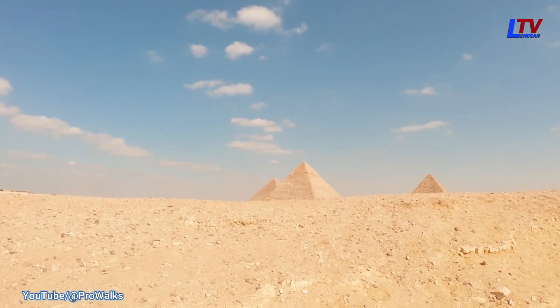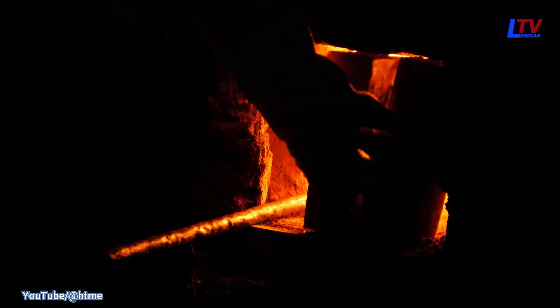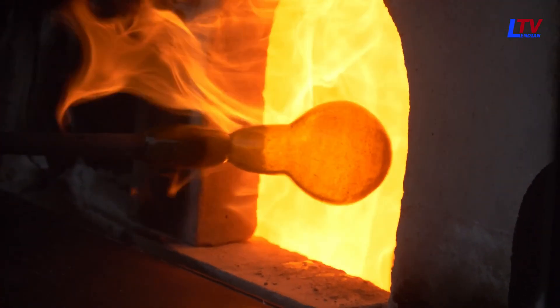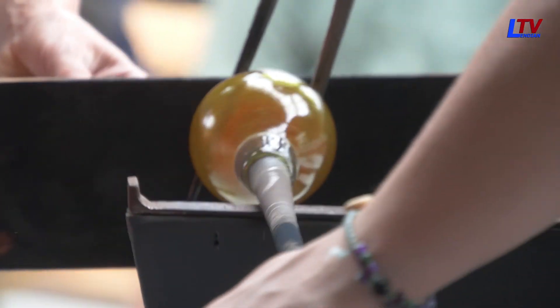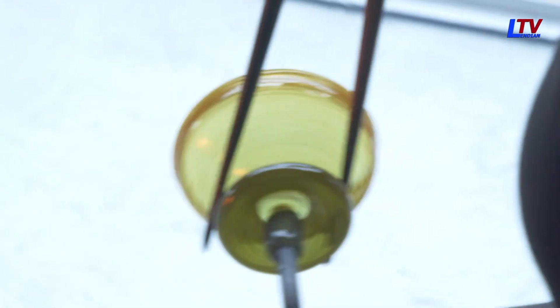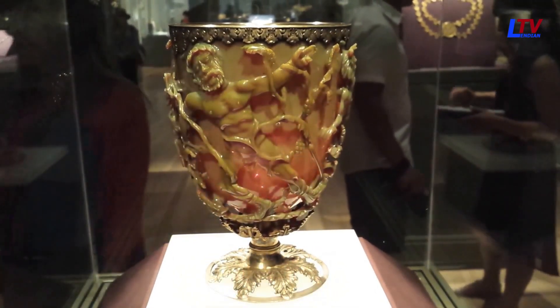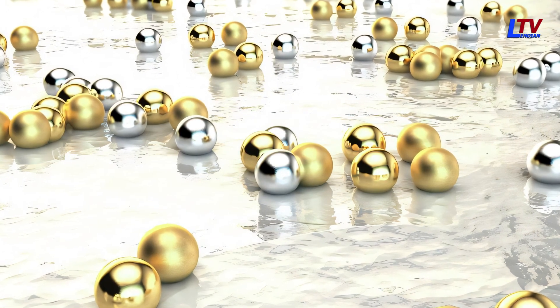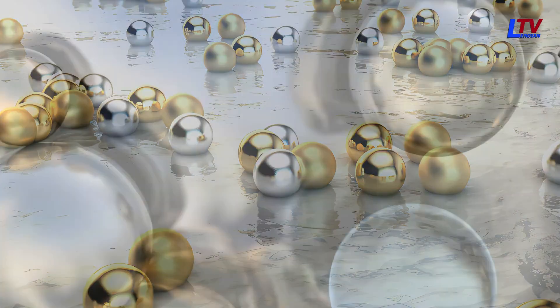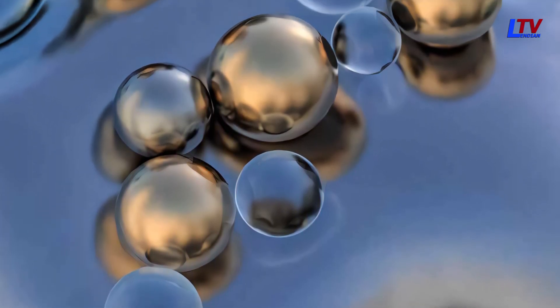The glass may have been created in a large block of clear glass, likely in Egypt or Palestine, which were major glass exporters. The thick dichroic blank vessel was probably crafted by one specialist and then passed on to another workshop of expert cutters. Given the cup's rarity and complexity, it was an expensive luxury item, and the secrets of its manufacture seem only to have been used for about a century. Around 330 parts per million of silver and 40 parts per million of gold were mixed into a typical Roman glass flux.